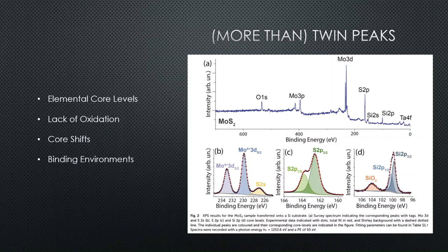One of the main concerns with exfoliation methods is the inadvertent oxidation or surface degradation of the material. However, the XPS analysis from this team revealed that there were no noticeable signs of oxidation or the formation of undesired chemical species. The XPS peaks also showed that the binding energies and the corresponding line shapes were in agreement with those of high quality, bulk, or conventionally exfoliated counterparts. This implies that the electronic signature is maintained without adverse effects that might otherwise indicate alterations in bond or defect formation.